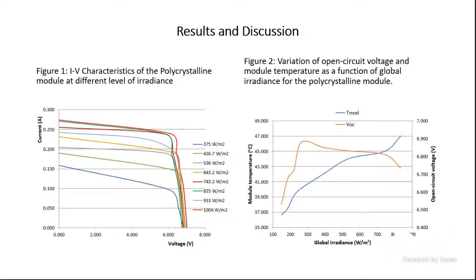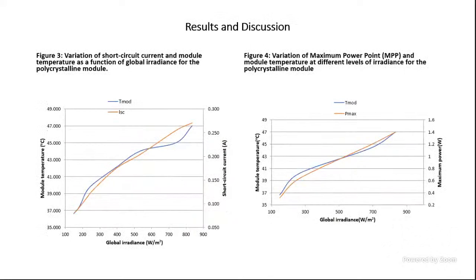And then the figure on the right, also comparing the module temperature and open circuit voltage of the module. Again, we can see that the open circuit voltage will increase, and then getting to a certain point, at a high temperature, the voltage doesn't increase anymore. And I can see from the plot, this is in accordance with other researchers in the field.